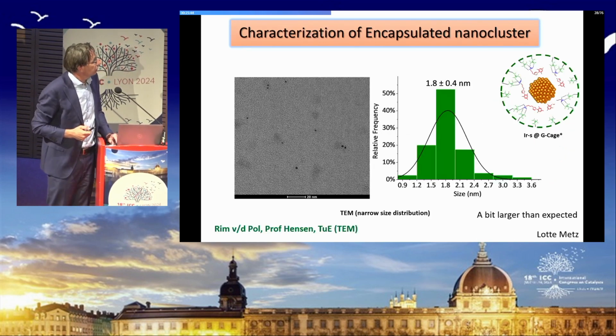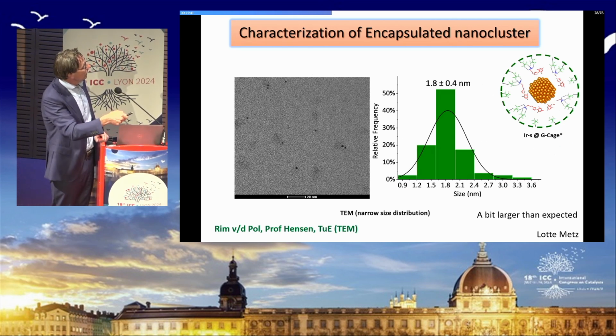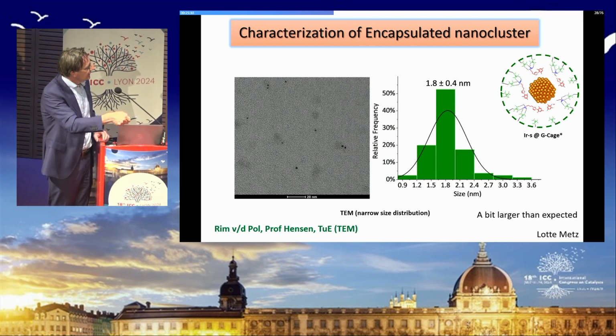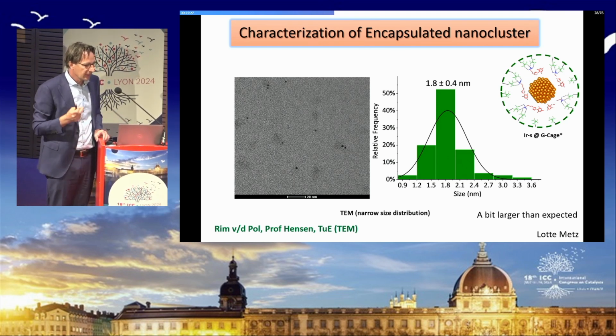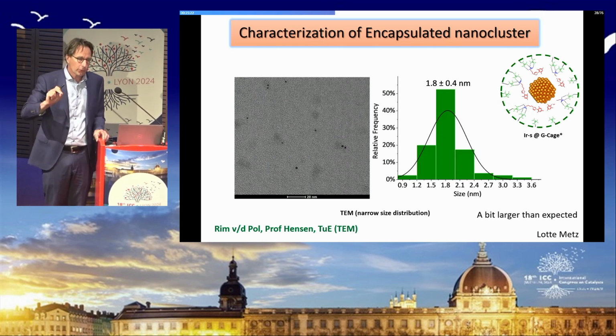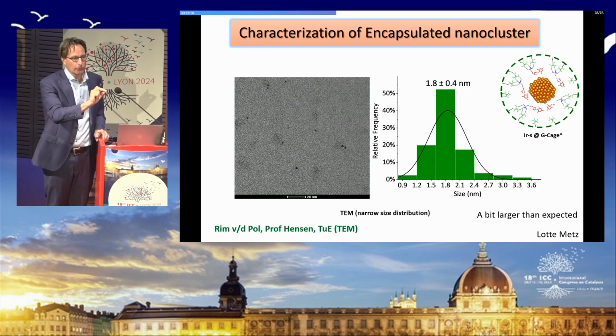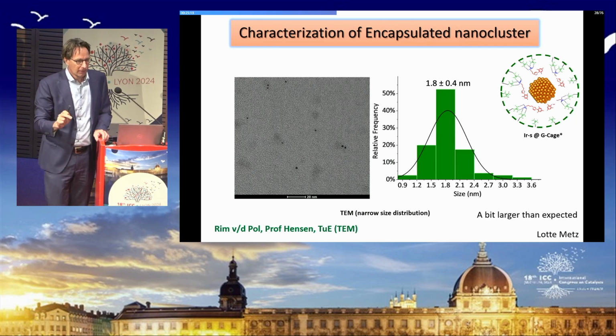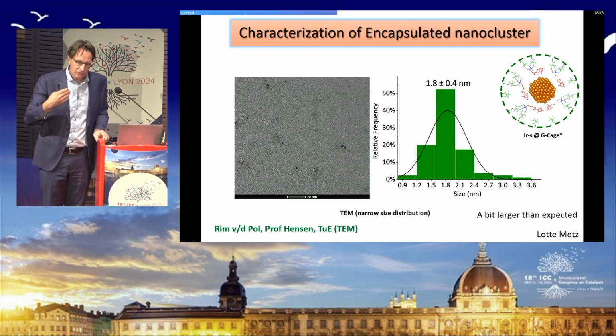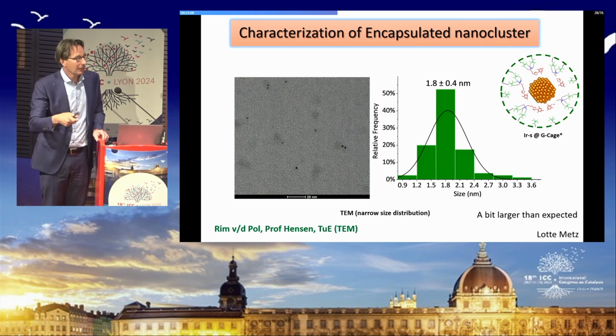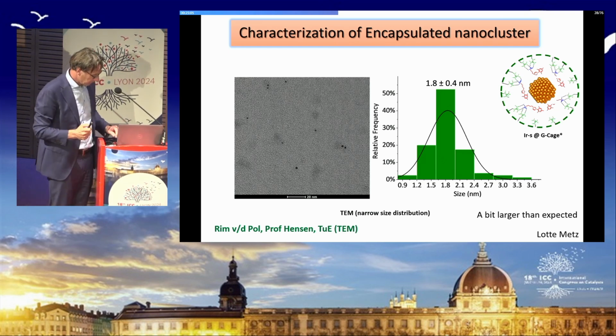So we subjected this to further characterization, and we looked at the structure. So we found nanoparticles with an average size of 1.8 nanometer. So for people that calculate very quickly, this is a little bit larger than expected. So these nanoclusters contain many more atoms than the 24, suggesting that during the nanoparticle formation, we still have exchange of metal complexes from one cage to the other. So clearly hydrogen bonding can lead to pre-organization, but it cannot prevent the formation of slightly larger clusters.